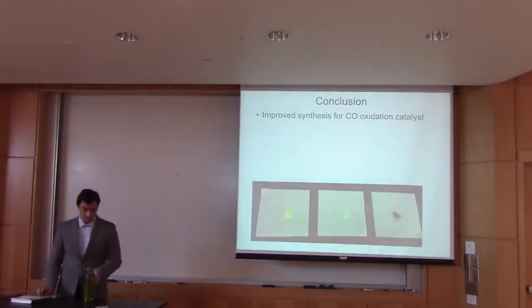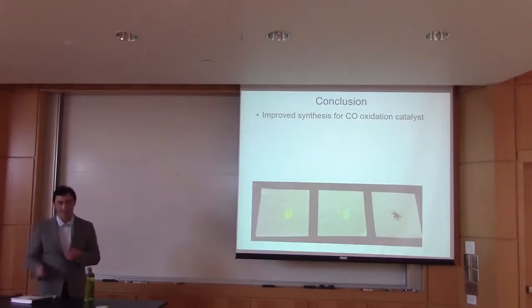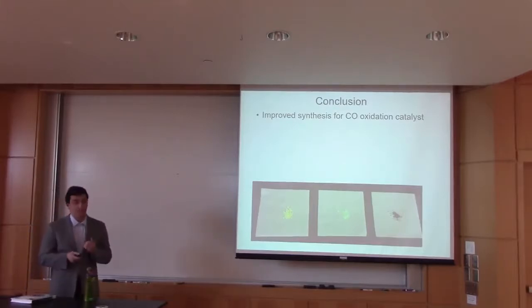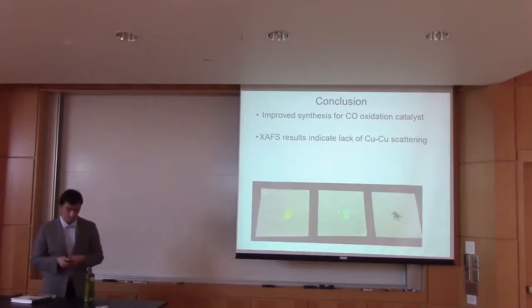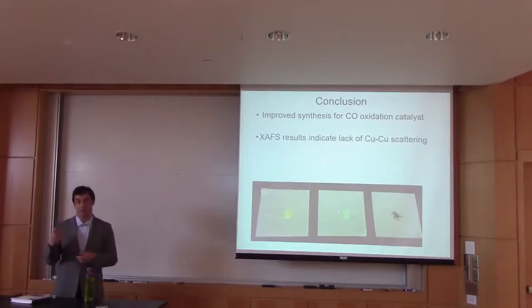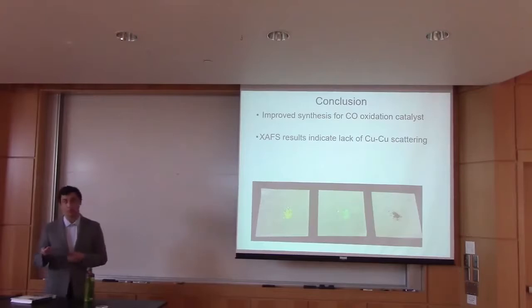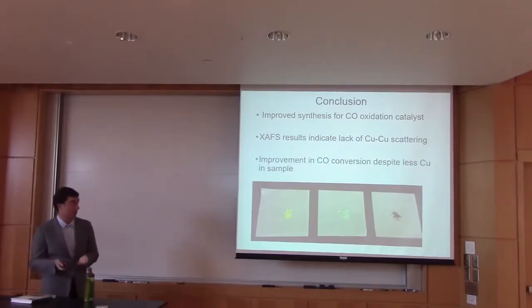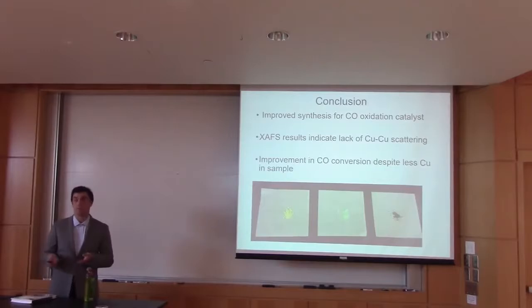So to wrap this up, in this work, I was able to improve the synthesis of this catalyst, was able to scale it up from the tens of milligram scale to the gram scale, where it could actually be tested for these catalytic efficiencies, and improve the step with low yield. In our XAS data, we saw the absence of this copper-copper scattering peak, which indicates we succeeded in minimizing the size of the copper oxide domain in our catalyst, which should mean an improved efficiency, which is what we saw. And again, improved efficiency despite less copper in the sample.